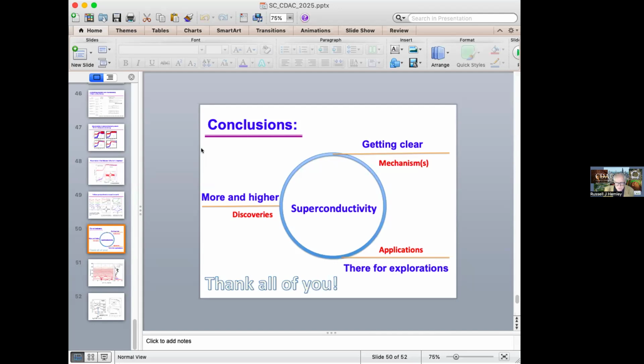I'm seeing some of the data for the first time on some of these systems. For example, the sample that we prepared many years ago on lanthanum hydride, the electronic Raman is very interesting. And the analysis shows that the gap you extract doesn't fit BCS, which is very, very interesting. And I understand that there are some unpublished data on H3S that also don't fit BCS. Are you aware of that? Have you thought more about why there's this difference? It's following that, but they give you a ratio like for LaH10, that's 8.8. This ratio can be compared; there's a lot of cuprates also around 10 or even 16. That indicates strong coupling. Yeah, right. Okay, we should follow up on that.